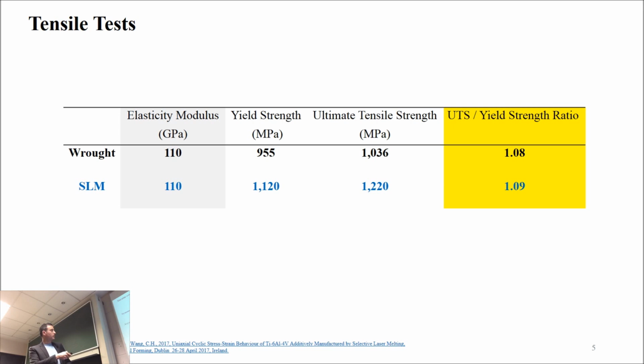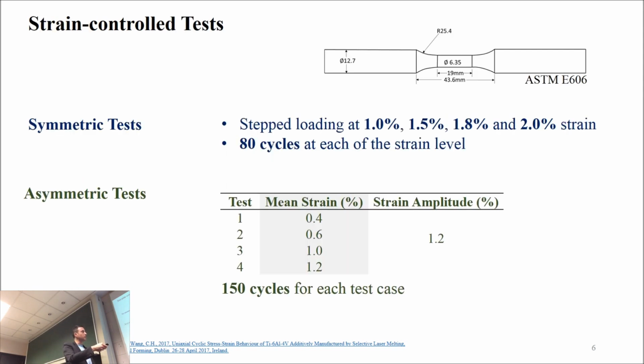Another set of tests we did was asymmetric tests, where we would like to see some other stuff, which I'm going to explain. So we did 4 different tests under a combination of mean strain and strain amplitude. We kept the strain amplitude constant and we played with the mean strain. For this kind of test, we did 150 cycles, because we thought that the material had the capacity to undergo this level of stressing without a premature failure.